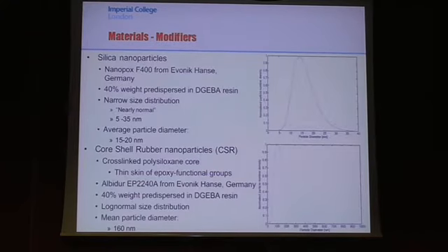So, what nanoparticles did we use? Well, we used some silica nanoparticles and some core shell rubber nanoparticles. So the silica nanoparticles were obtained from Evonik at 40% weight, pre-dispersed in the resin already, which makes things easy to work with. So the silica nanoparticles have a relatively narrow size distribution. We can describe the distribution as nearly normal. So about 95 to 98% of the particles have a diameter between 5 and 35 nanometers. So they're very small particles.